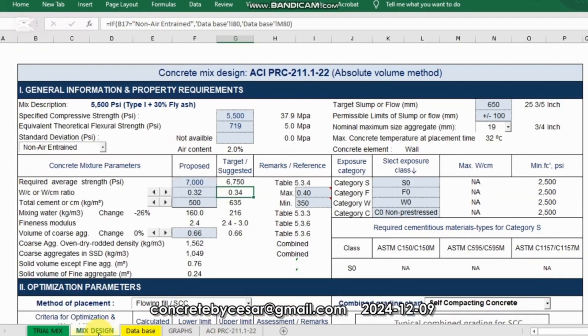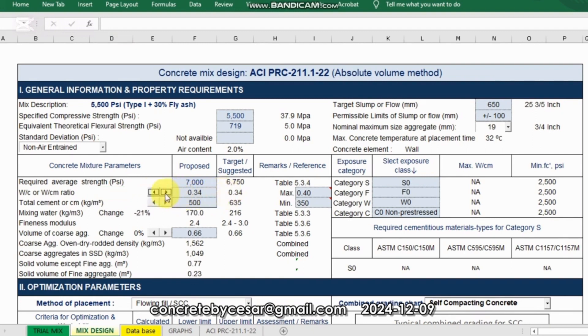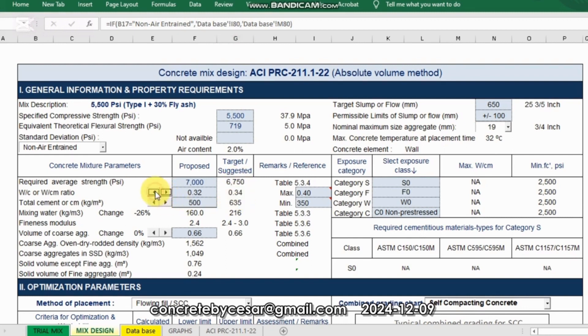Going back to our mix design, for the suggested 0.34 water-cement ratio and considering the use of 30% Class F fly ash as cement replacement — for someone working in ready-mix for a long time, you already know you have to reduce the water-cement ratio considering slow strength gain when blended with this type of fly ash. From 0.34, we have to reduce by at least 0.02. It also depends on your available materials — you may need to reduce further, down to 0.30 water-cement ratio. Typically, Class F fly ash results in slower strength development compared to pure cement Type 1 or 2, although it tends to achieve much higher strength at a later age.